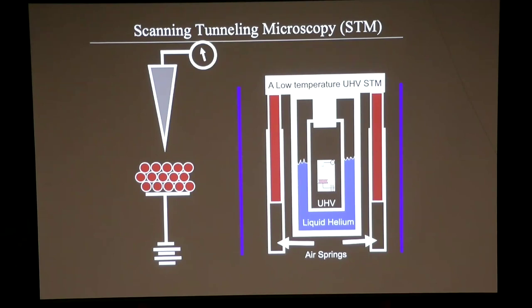Because the tip is only a few angstroms from the surface, you have to put it in a vibration isolation room. You have to isolate it from ground vibrations by putting it on air legs. If you want high resolution, you have to go to low temperatures. And finally, if you want to keep your surfaces clean, because the scanning tunneling microscope is a surface sensitive probe, you have to have ultra high vacuum.